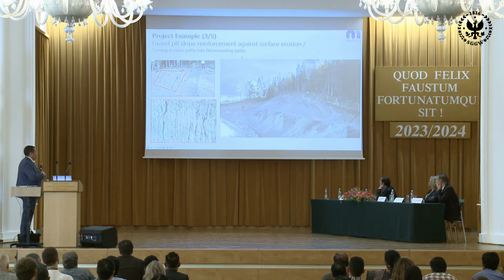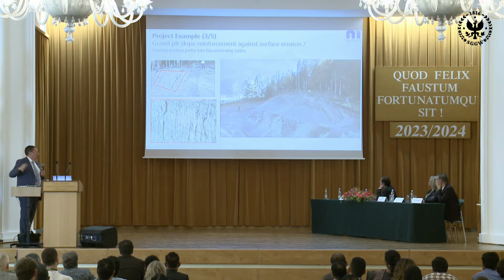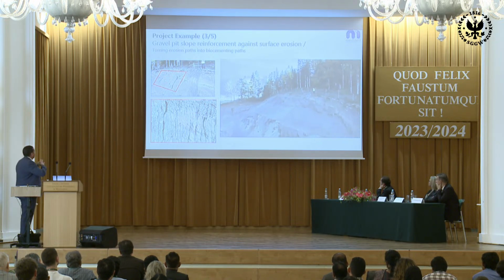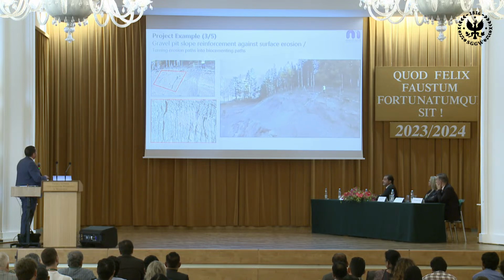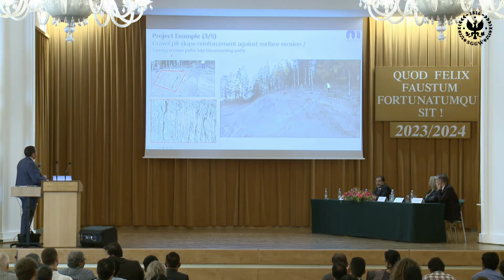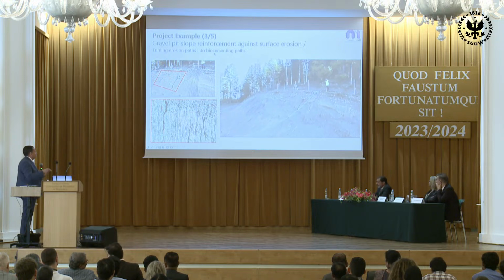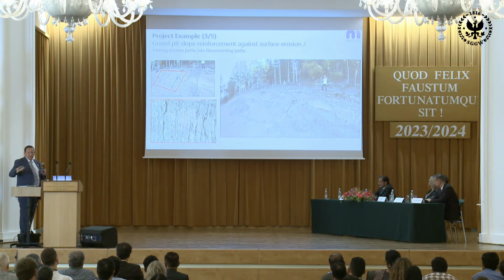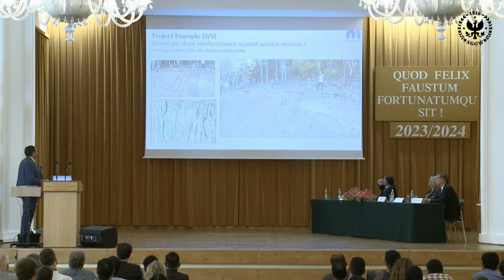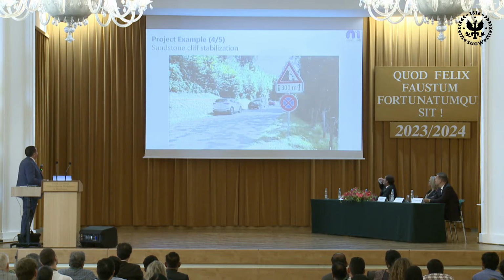Third example is gravel pit slope reinforcement. When you have those large areas that are facing erosion, to stabilize them, basically what we do is turn the erosion path into a biocementing path by simply spreading the solution on the surface and getting the needed stabilization.